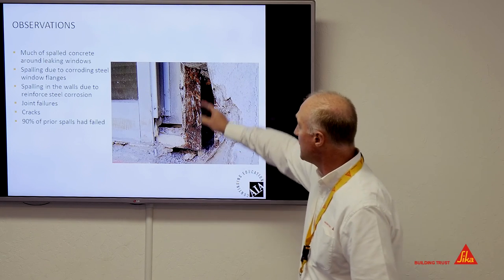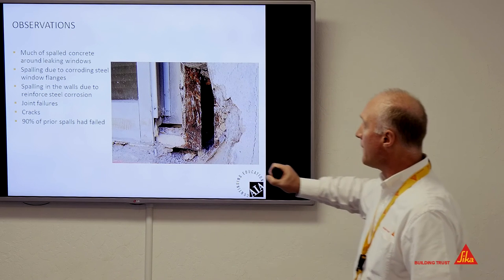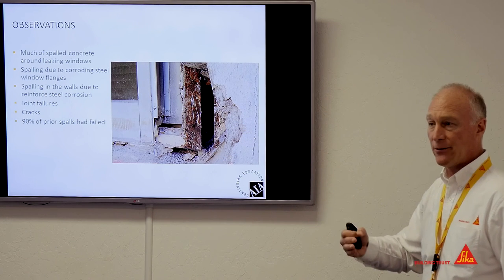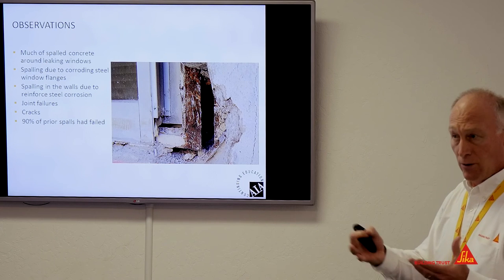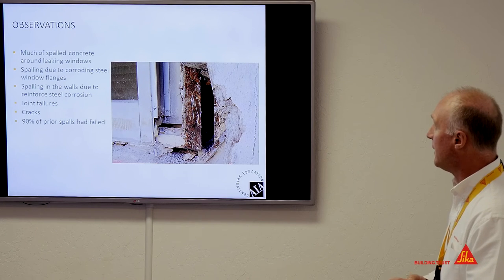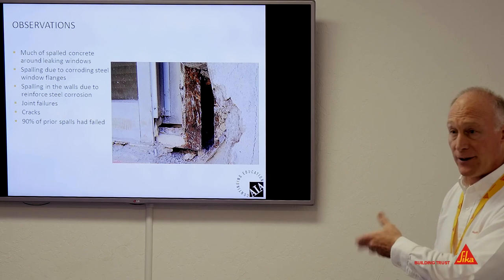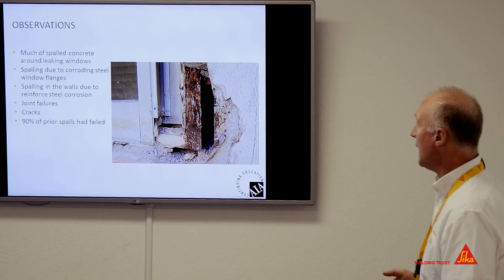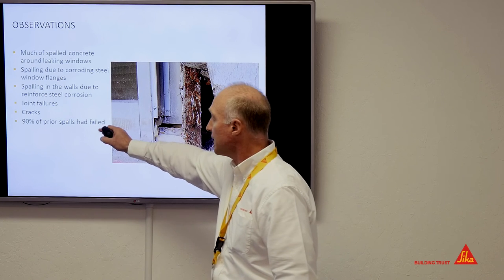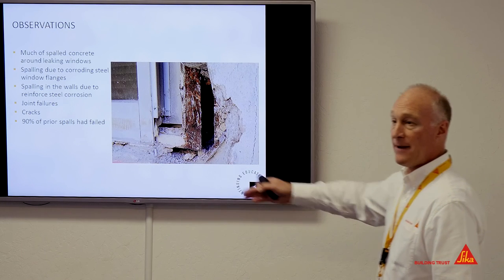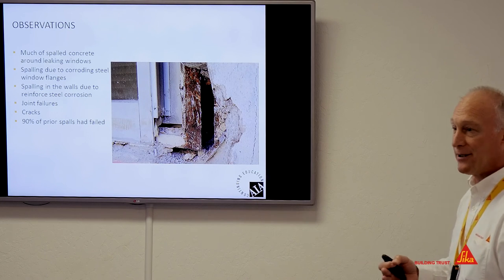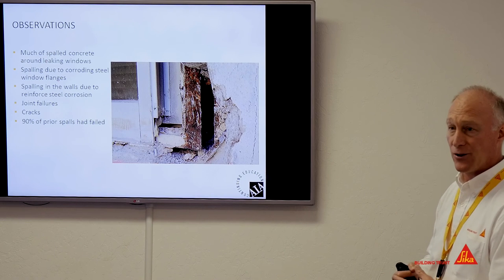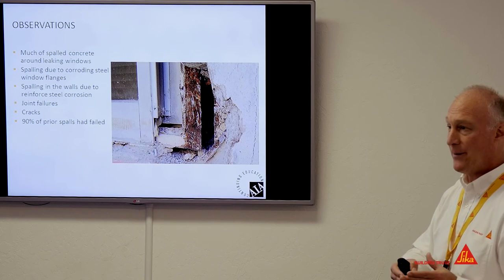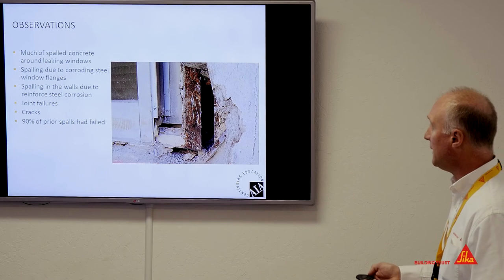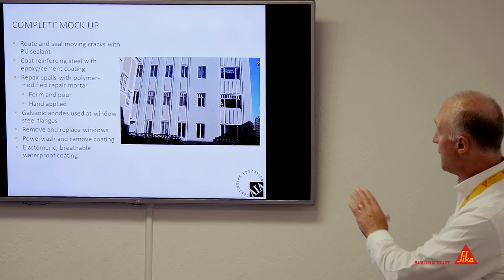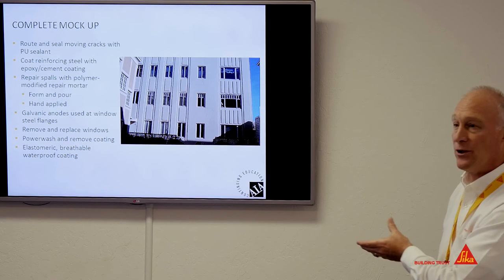They had the steel frames that were corroding, but they also had a lot of spalling within the concrete itself. So it was just normal reinforcing steel corrosion. Failure at joints, a lot of cracks, as you saw in some of those previous photos. And a lot of spalls that had been previously fixed had actually failed. Now, some of them were 20 years old, so they got good life out of the spalls. It's not to say that all those spalls were problematic, but they were also dealing with that. And this was how it looked at the completion of the mock-up.